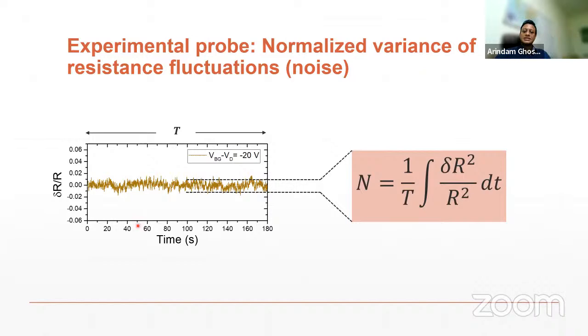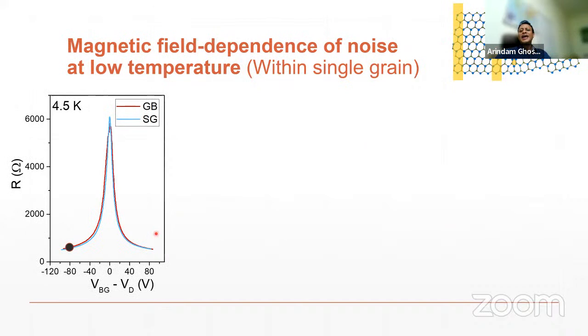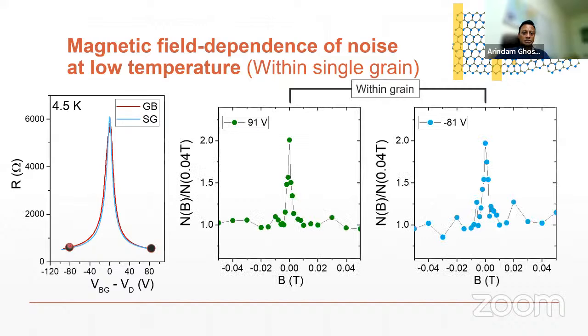Okay. Now what happens within the grain? Suppose I have a grain boundary, but I measure away from the grain boundary. And I measure at a gate voltage, say for example, at 2 gate voltage. I can measure at high gate voltage on the hole side and a high gate voltage on the electron side. You can see that the noise, which is in this region, comes down exactly by a factor of 2 when I apply a magnetic field, because magnetic field is removing the time reversal symmetry and the noise is coming down because the Cooperon contribution is removed, and it is exactly by a factor of 2 reduction.